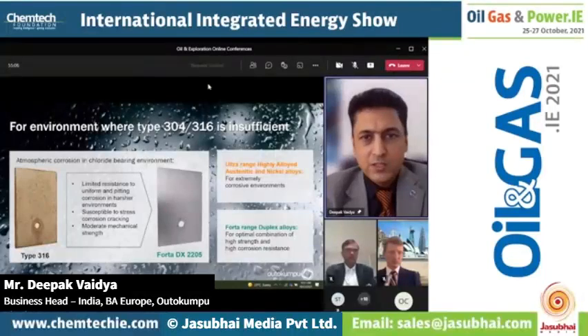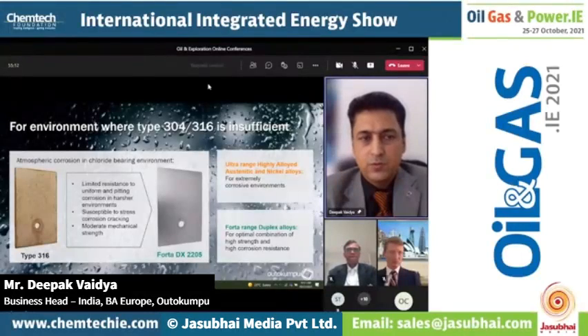Surely there are environments where standard 304 and 316L are not enough. We have seen a lot of corrosion; many people have used them in different equipment and come up with a problem. So one thing we need to understand is that stainless steel doesn't mean that it will not corrode. If you use a wrong grade, it will definitely corrode.